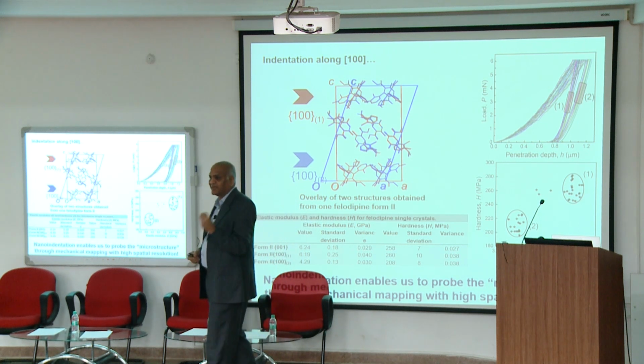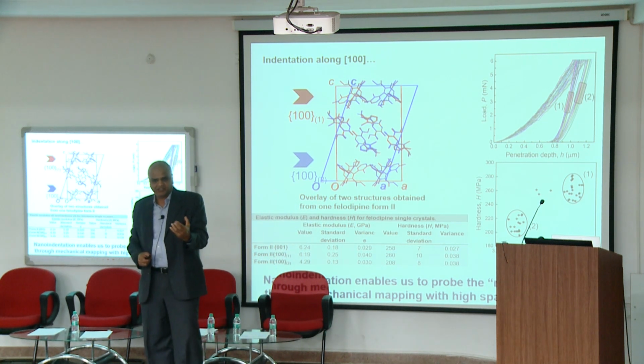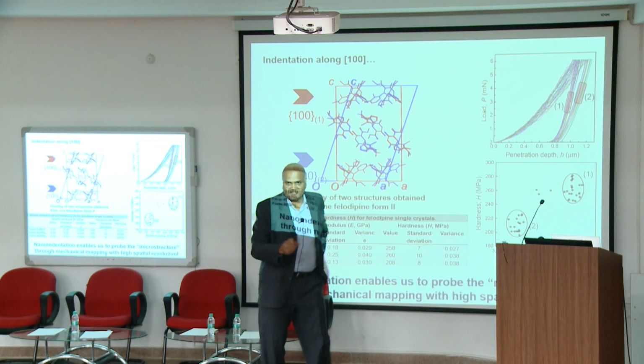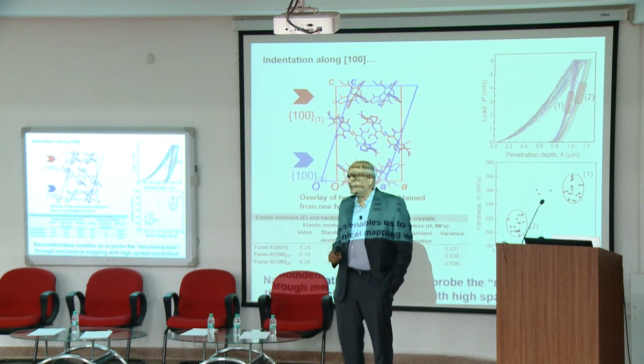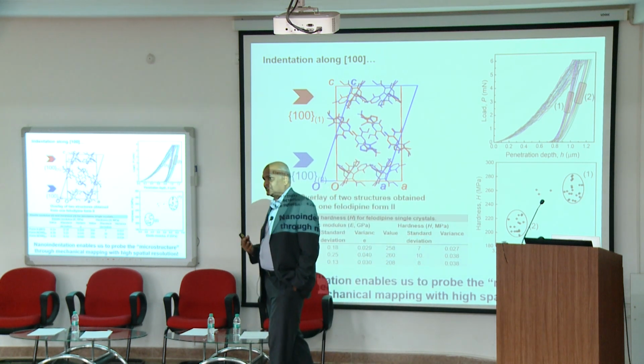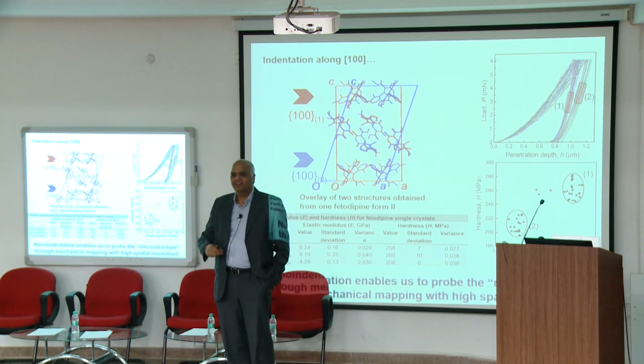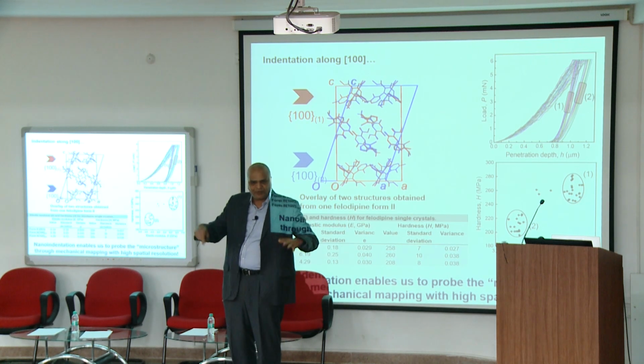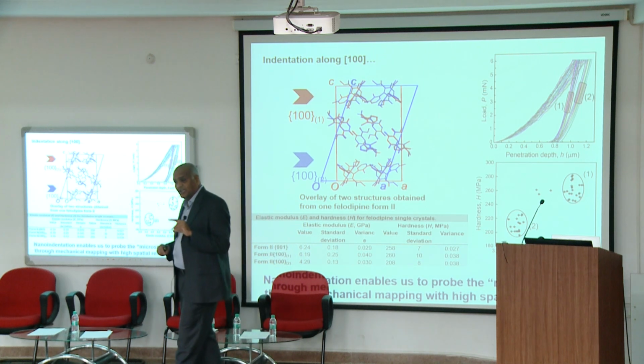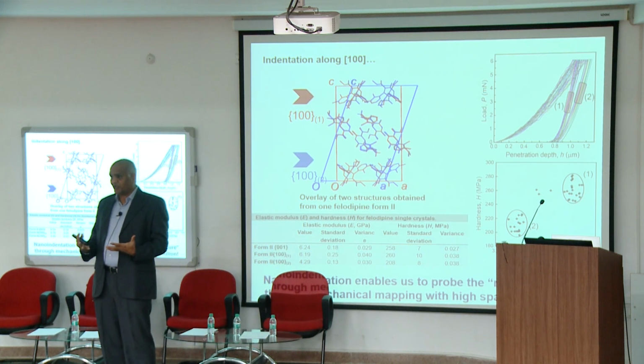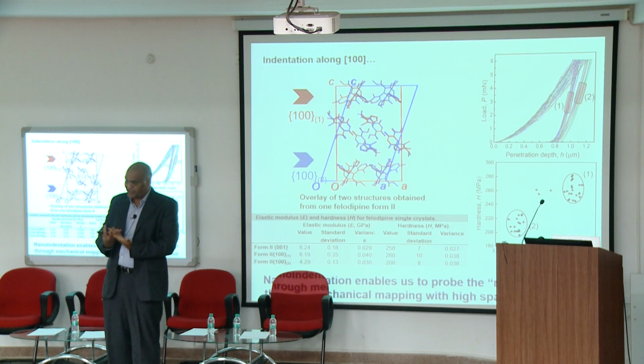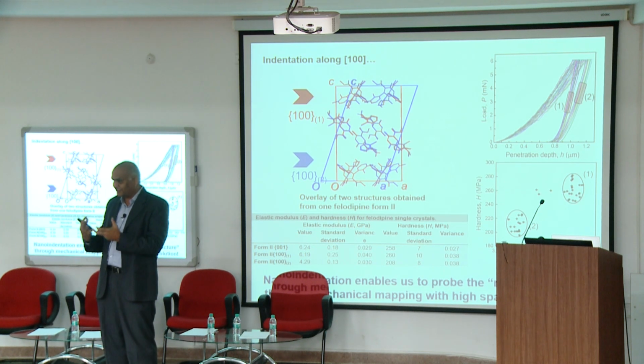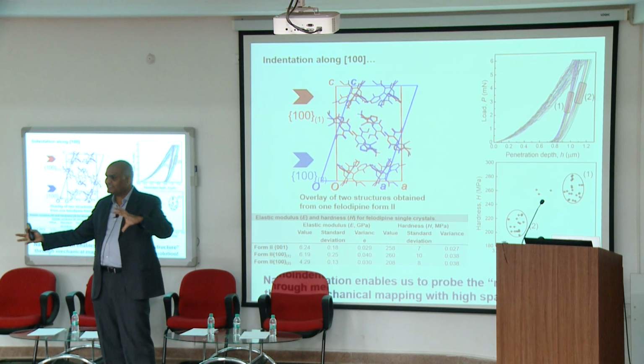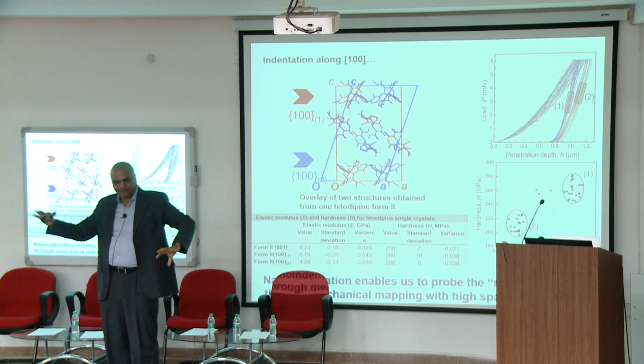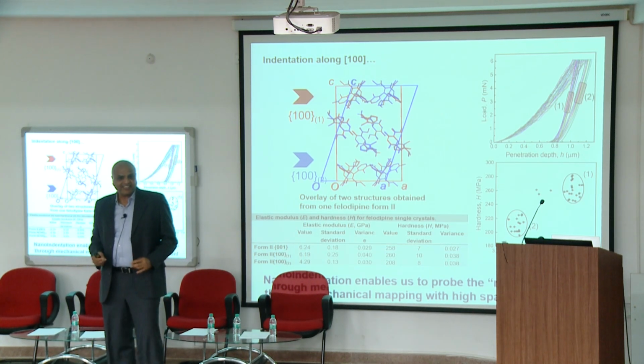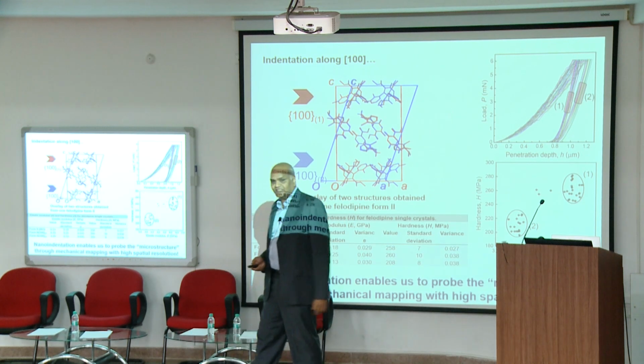I can actually look at the microstructure of the material. So my young colleague Jay does this in your school. He is looking at steels, which have martensites and austenites. So he goes with a nano indenter and probes, maps the mechanical properties. So if you have an intergrowth polymorphism, you have essentially a microstructure to the material, right? Even if it is a single crystal, there are domains of form 1 and form 2 and whatever form. You can actually do this, right, with the nano indentation.